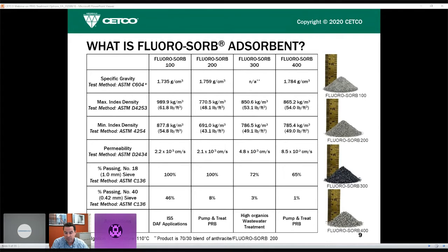FLUORO-SORB 200 is a little bit bigger in grain size. It ranges from 0.5 millimeters to 1 millimeter, and it can be used in pump and treat. And that media we also mix with, as I mentioned, anthracite, and that's used in situations where you might have high organics. Because our media absorbs organic compounds, we put the anthracite in there to maintain high hydraulic conductivity. And then lastly, FLUORO-SORB 400 is a larger media, and the particle size is the biggest, and it ranges from 0.5 millimeters up to 5 millimeters.